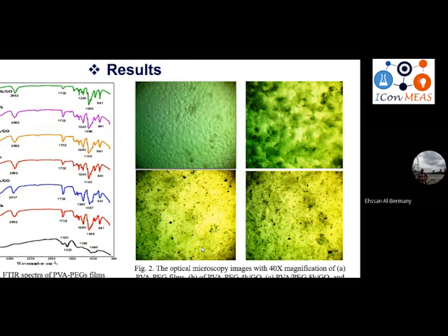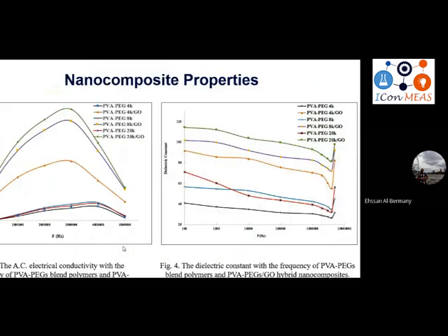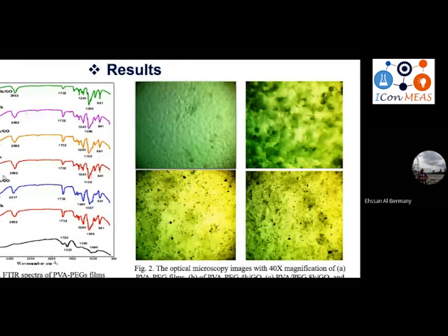The FTIR shows us, for this material, we compared it first with the polymer blend, then with the graphene oxide. So we can see most functional groups of both materials, the blended polymer and GO, representing all the functional groups. We can see that these functional groups are similar with small changes in intensity, or sometimes a little bit of shifting in the peaks. This confirms the preparation of graphene oxide and also the successful preparation and connection between these materials as a physical connection. There is no chemical interaction or bonding represented here.